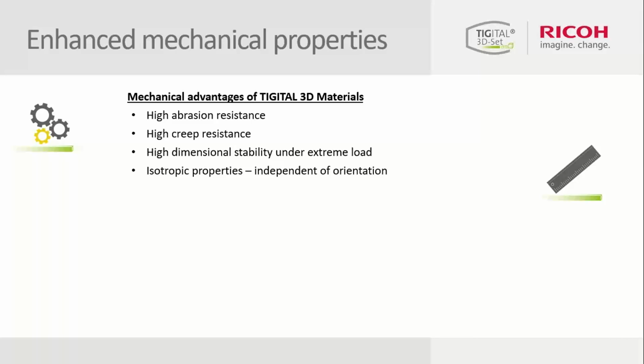starting from the mechanical properties. So in terms of mechanical properties, this material has very good abrasion resistance, and also a very good creep resistance, which means that when they are submitted to mechanical stresses, even for a long period of time, they are able to maintain their initial shape. Another advantage compared to most of the thermoplastic material available for SLS is the possibility to achieve isotropic mechanical properties, which means that the mechanical properties of the material are independent of the printing orientation.